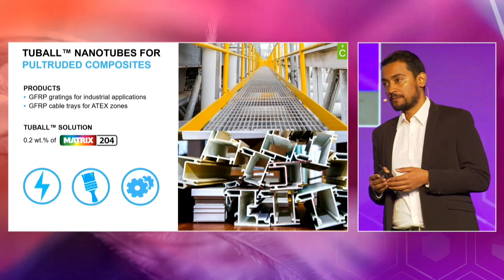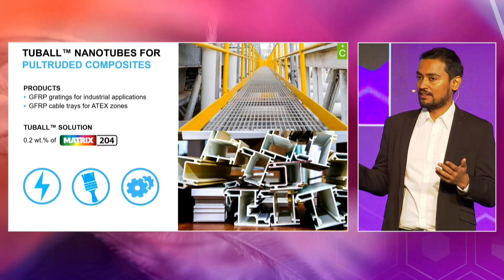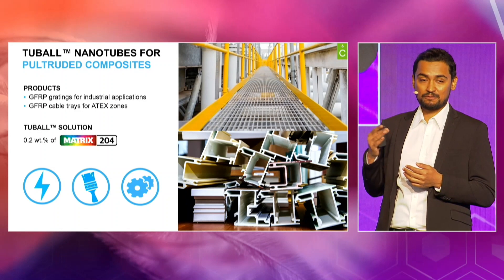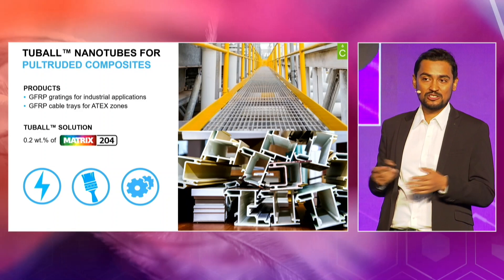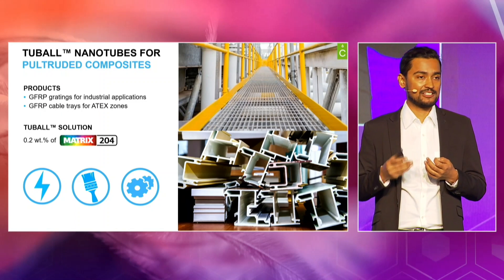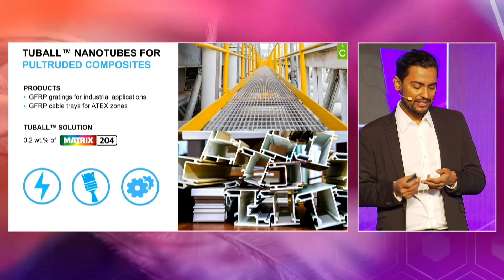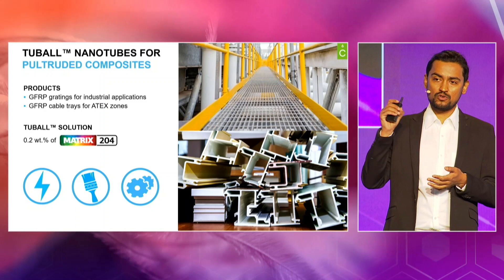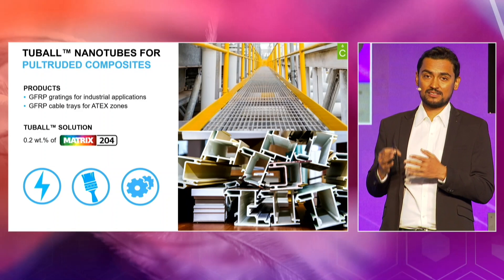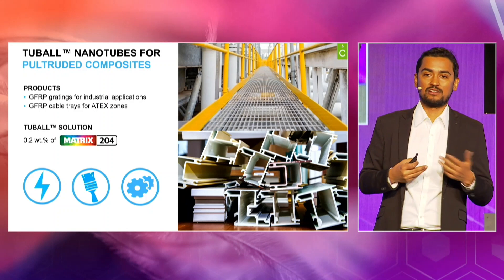Same with pultruded composites. One special point about pultruded composite is that it is by value extremely cheap. So adding nanotubes to pultruded composites doesn't increase the price to an extent that it becomes impossible to buy. This is one of the great myths we have been busting — that nanotube addition makes the polymer very expensive. You can see this, for example, in cable trays or gratings, where you add extremely low amounts — sometimes 0.2% of nanotubes — and get a whole range of conductivities. These pultruded parts can now be used in EX environments, that is explosive atmosphere environments.